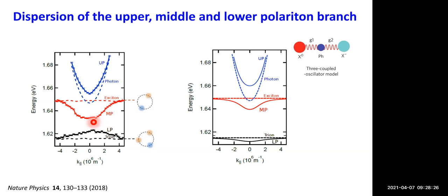And what this does is overwhelm the weak trion-cavity repulsion that you are seeing over here in the model system. The origin of such an interaction, you can understand in terms of an exchange between an electron and a neutral exciton and the negatively charged trion. This gives the delocalization energy of the trion's electrons, which causes it to look like this, an attractive feature rather than a level repulsion that you would expect normally in the trion-polariton.